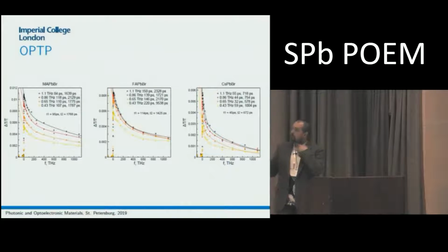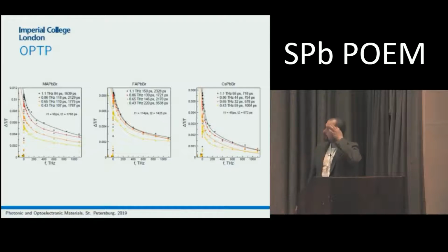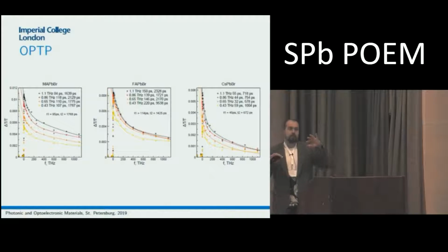And if we look at the spectra and temporal characteristics, and I believe this hasn't been reported, we can see in some materials, for example cesium, at some frequencies the temporal constants of the exponential decay, which is mostly used for these materials, differ twice between different frequencies, like 0.4 terahertz and 0.5 terahertz. The characteristic times would be 2 times different, which may be associated with different interactions happening within carriers and lattice, or carriers and phonons.